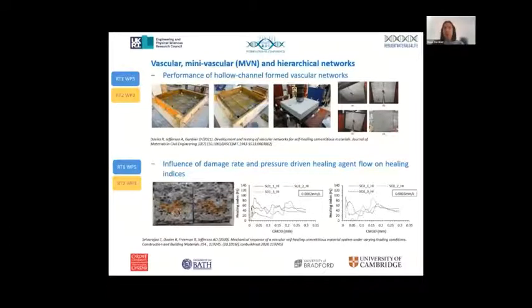So when we're thinking about these closed loop systems in vascular networks, we really want to make sure we have sufficient pressure to drive our healing agents into the zones of damage, because often capillary force alone is insufficient. So we've done some studies looking at what's the influence of pressure, what's the influence of damage rate on how successful, how efficient our healing can be. And we've actually achieved a stage whereby we can heal damage simultaneously as damage is occurring, which is really useful for things like dynamic damage scenarios. And we've also confirmed the pressure of not only pressurizing the healing agent, being able to find that optimum pressure for different types of crack and also different crack widths.